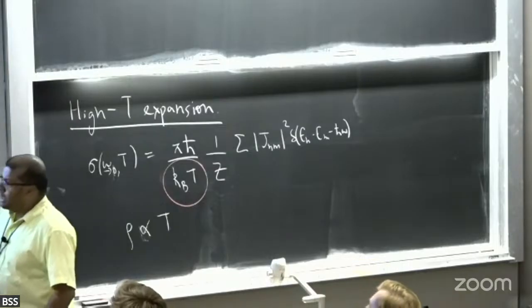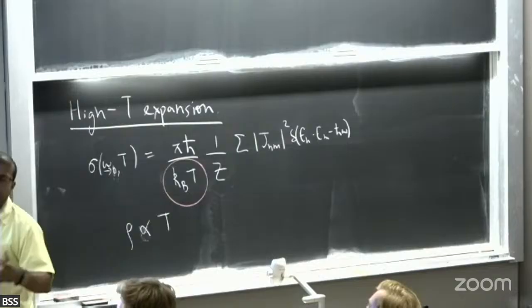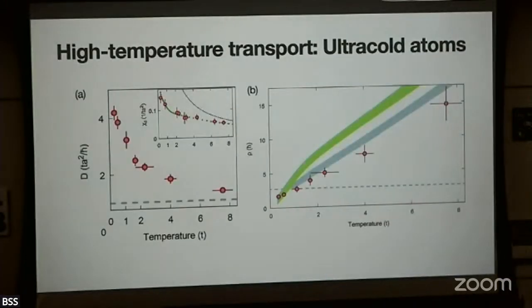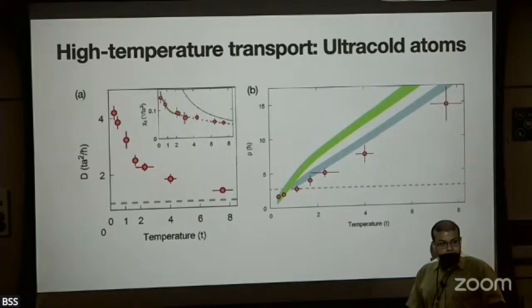Okay, so let's first look at whether this is relevant at all. Now, again, the important point to note is this is something you obtain when the temperature is larger than the bandwidth. Okay, so in the cuprates, you're certainly not seeing evidence of this when I talk about T-linear resistivity. Actually, for that matter, this is not relevant for any electronic solid because you always have to deal again with phonons. But as it turns out, you can look at a very interesting system which can be probed experimentally.